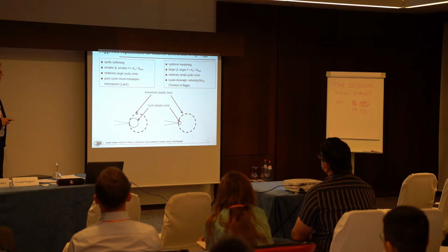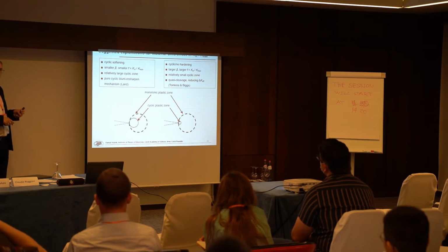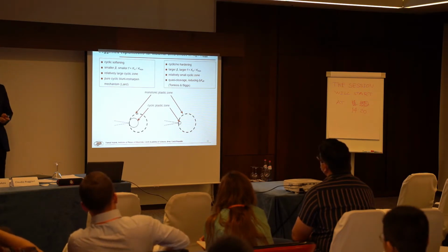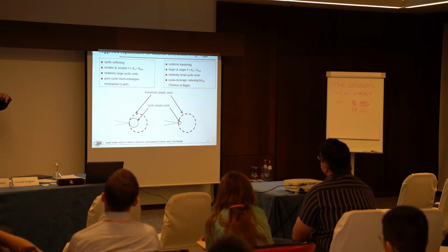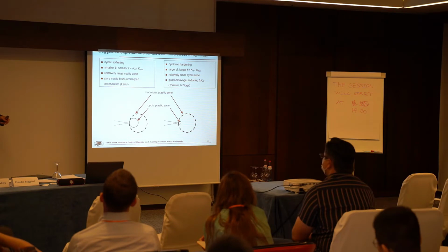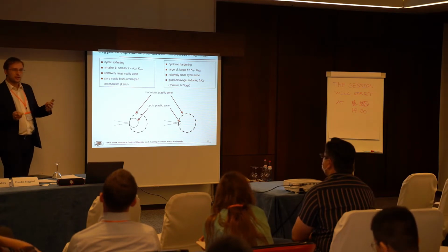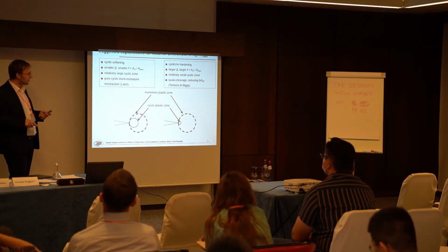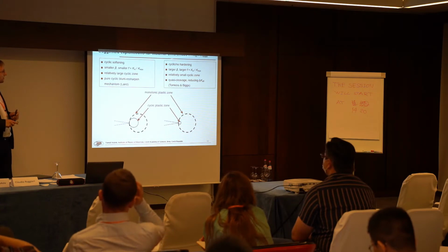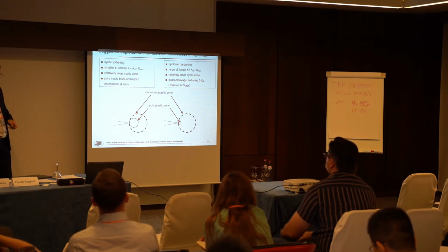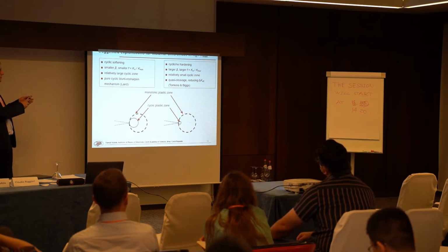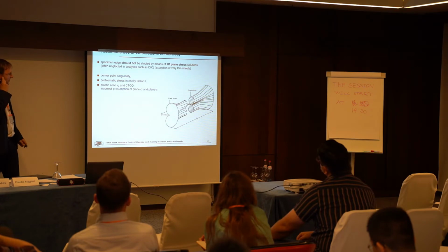And also another idea is that the mechanism of fatigue crack propagation might not be fully given by the cyclic plastic deformation, blunting and resharpening mechanism, but also it can be partially given by microcracking. And this effect could also be taken into account if we take different behavior according to the beta parameter, which is technically then not really a value of crack closure, but it's the same effect on the effective delta K that we obtain after taking it into account. So this is our idea how to take these effects into account, and we can then study differences between materials and between microstructures. Here's a few things that we should consider.